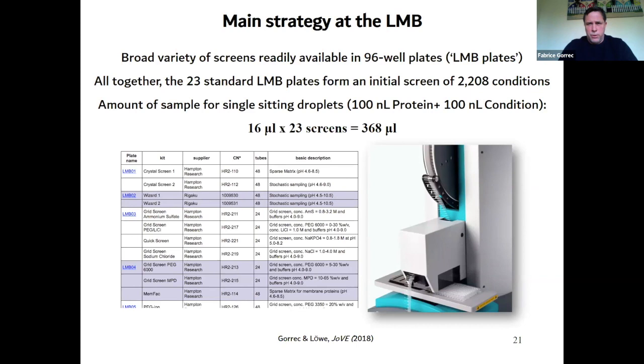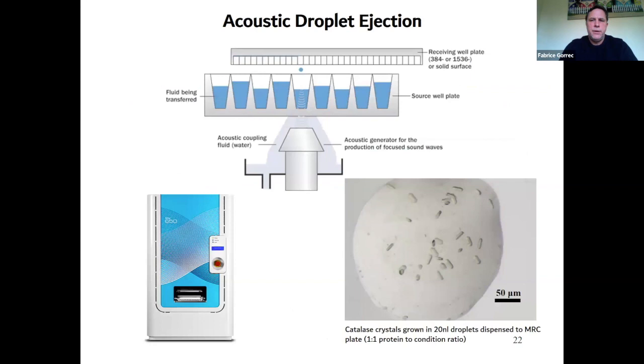Fortunately, there's a technology that will enable us to reduce the required amount of sample. So we're going to integrate such technology. It's called ECHO, which is not a classic liquid handling technology. It's acoustic droplet ejection technology. So it's able to do much smaller drops, and we tested it with 10 nanoliter plus 10 nanoliter droplets, which work really well. And we are going to integrate this at the protein crystallization facility very shortly.